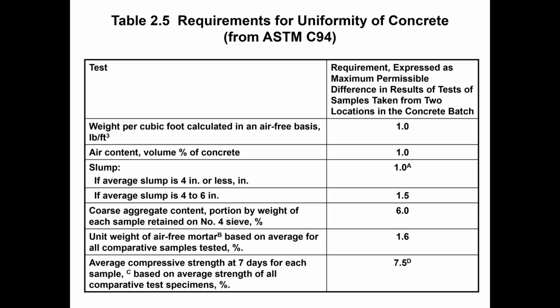So if, when doing this uniformity test, it's found that some of these requirements are not met, that's usually an indicator that the truck needs to be removed from service and it needs to be renovated, which means that the barrel may need to be cleaned out. Maybe the mixing fins within the barrel have worn so that they're no longer as effective as new fins would be, so the fins may need to be replaced within the barrel. But generally, if the truck cannot meet these requirements, then that truck should not be used for production.